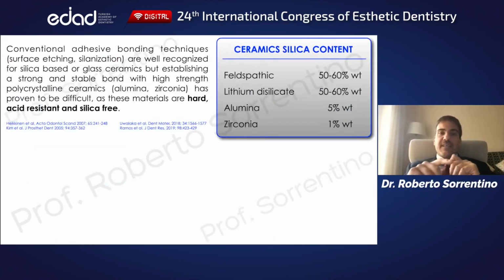However, the acid etching technique can be used only with glass materials, just like feldspathic and silicate-based ceramics, but not with polycrystalline cores, such as alumina and zirconia, since the latter contain less than 5% in weight of silica particles, the only component that can be primed by acids.